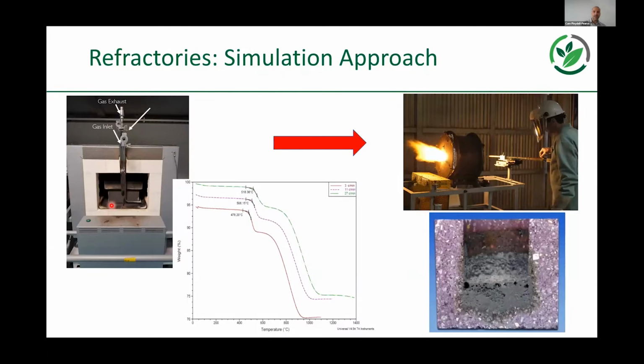Which leads me on to our simulation approaches. At the same time, we're developing approaches for physical simulation of how those refractories are actually behaving in service. And we're doing this through an approach of increasing complexity. So first of all, we're looking at atmospheric degradation of this material, so how it oxidizes. And it's particularly susceptible to this because it has this carbon in there. Now, you could argue, why is the carbon in there in the first place? And that's because we need to, ironically, increase the thermal conductivity of the material to a degree to account for the fact that a lot of the applications are in fact transient. So imagine a ladle being filled full of molten steel and then emptied. And we need to account for protecting against thermal shock.